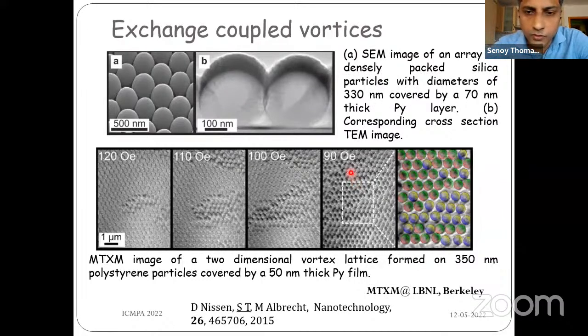So this is what you could basically see in this MTXM image, where one could see at the switching field a large domain of vortices with a similar polarity as well as chirality is present. This is basically due to the exchange coupling between the nearby magnetic vortices. As a next step, we wanted to investigate the influence of temperature on the magnetization reversal process.